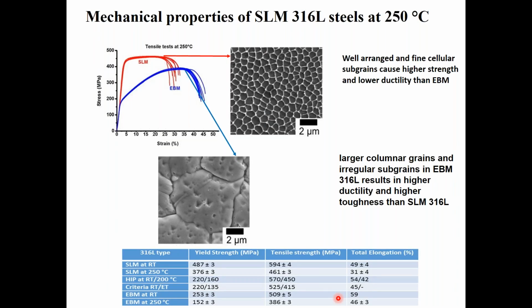So now I will show you, if we increase the temperature from room temperature to 250 degrees centigrade, how this hierarchical structure contributes towards high temperature mechanical stability. At 250 centigrade, you can see the SLM samples show superior properties, high mechanical strength, and they still keep the hierarchical structure, the heterogeneities in the SLM as-built sample. So we still find the structure stable at 250 degrees centigrade, and we get very high properties compared to EBM and conventional steels.